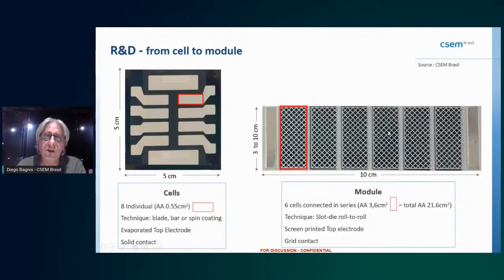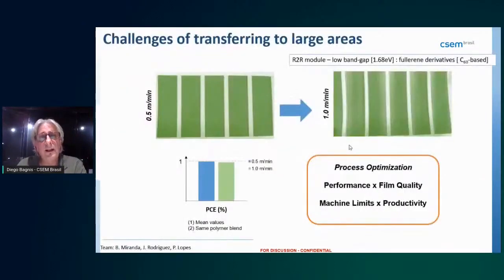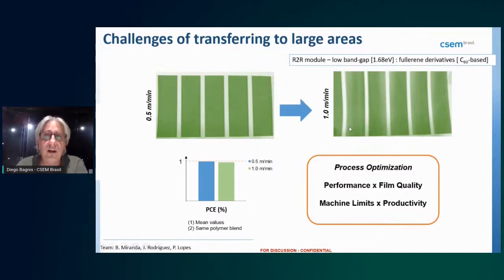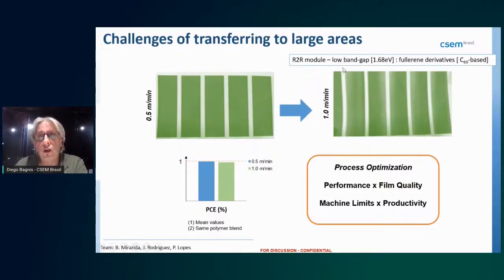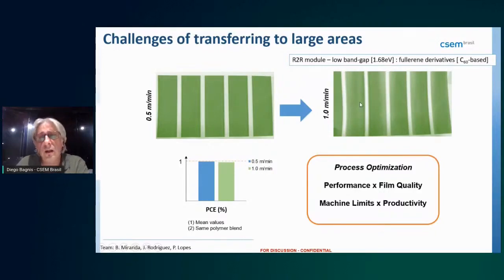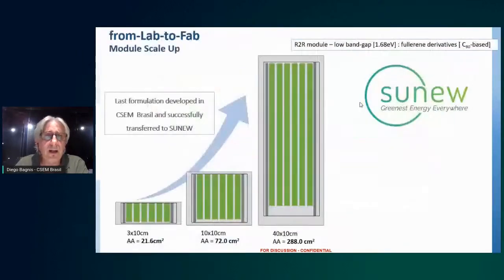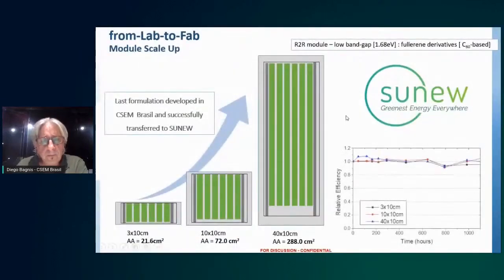Our basic module is used to gather statistics on performance and lifetime. When scaling up, aesthetics becomes an issue too. Increasing the speed of the production line, as required, initially gave poor aesthetic quality even though the performance was similar. It was therefore necessary to adjust parameters to achieve both good visual quality and good panel performance.